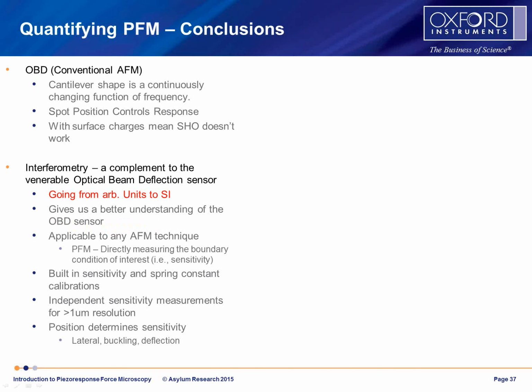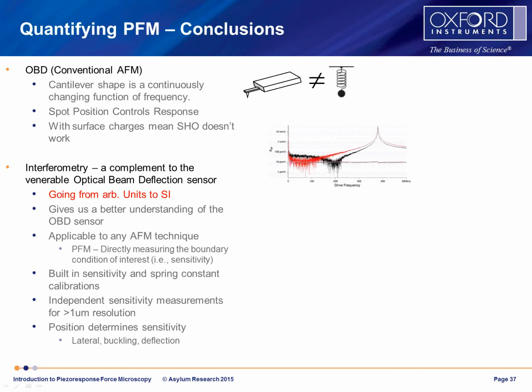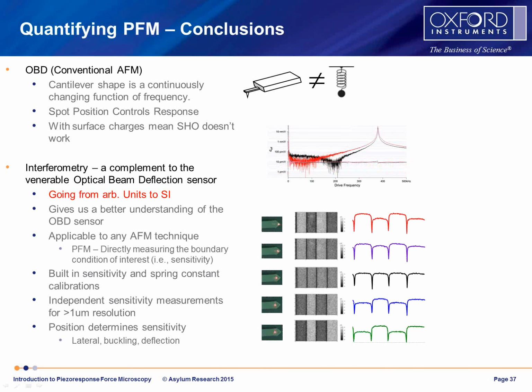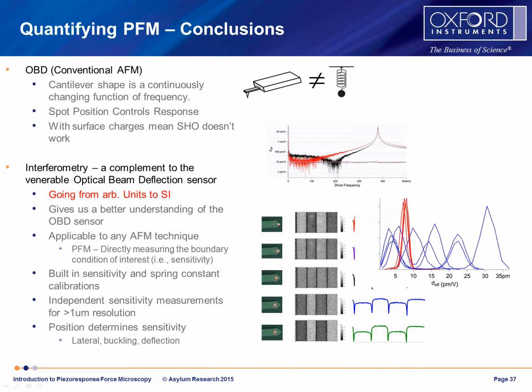In the case of the PFM measurements, as I said, the simple harmonic oscillator model probably doesn't work all the time, at least for charged surfaces. The interferometry response over that tip is actually very interesting. Maybe now we have a window onto directly what is happening underneath the tip. At least in the case of the PPLN, it gave us nearly ideal results, at least when that optical interferometer is positioned properly. So we see the domain responses are almost exactly equal, and the distribution of the effective piezo sensitivity goes from being very scattered to very, very tight.